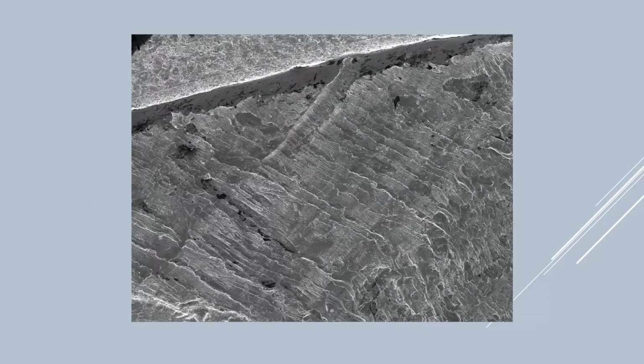I wasn't allowed to cut this up. I was going to go back for litigation. So I was only able to take a replica with that silicone rubber. It's not that good though. When you look at that, you see these kind of curved marks. Those aren't striations, fatigue striations. Those are beach marks. And that's about as high a magnification as I could get out of this particular brand of silicone rubber. It's not that good. But there are other brands of silicone rubber that will give you better resolution. Still, just looking at that, I would say it's fatigue. But since it's a litigation, I better have a bit more ammunition than just the fact that it appears to be that way.